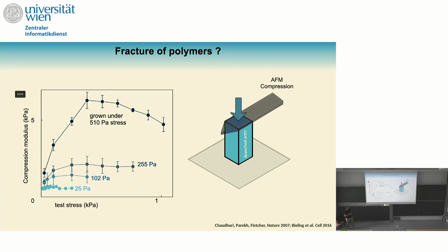So if you do that and you measure the modulus in compression as a function of the stress that you apply, so if the system has been grown under, let's say, normal condition in the sense that it had been grown at low stresses, it has some modulus that is very small. But then if the system has been grown under hard condition in the sense that it has been grown under large stress, so I apply to my system and let it self-assemble in this very weird environment where I'm applying stresses, and then once it's assembled, then I apply again deformation to probe its response. You see it's stiffened a lot by orders of magnitude.